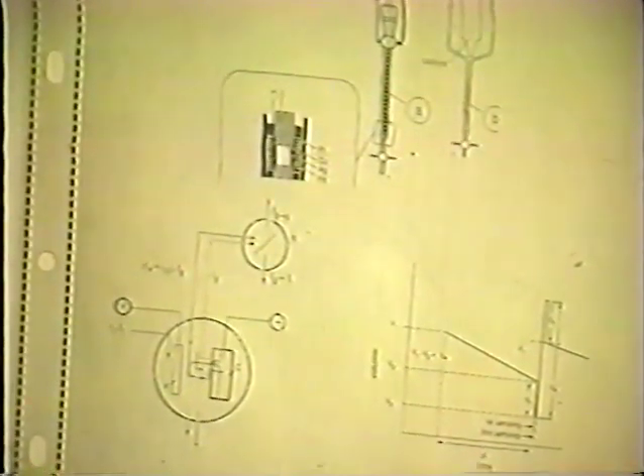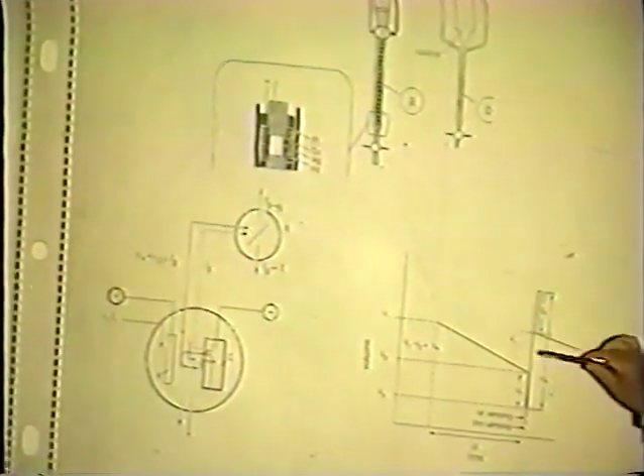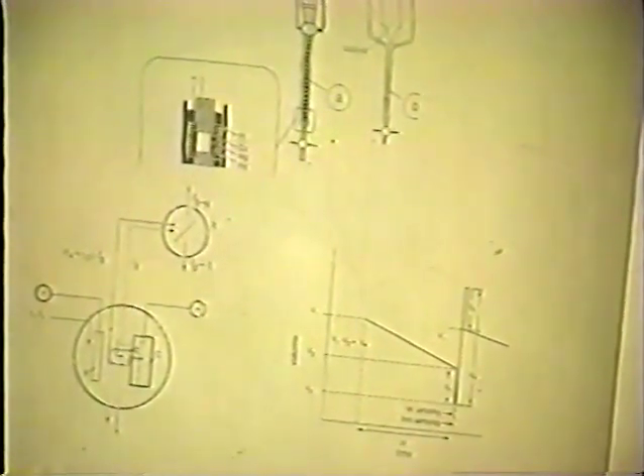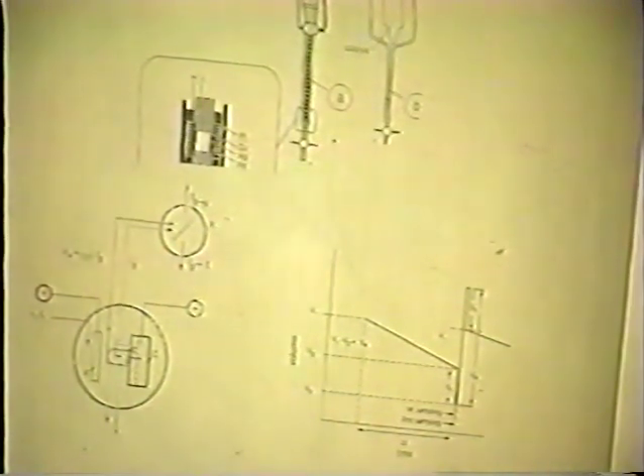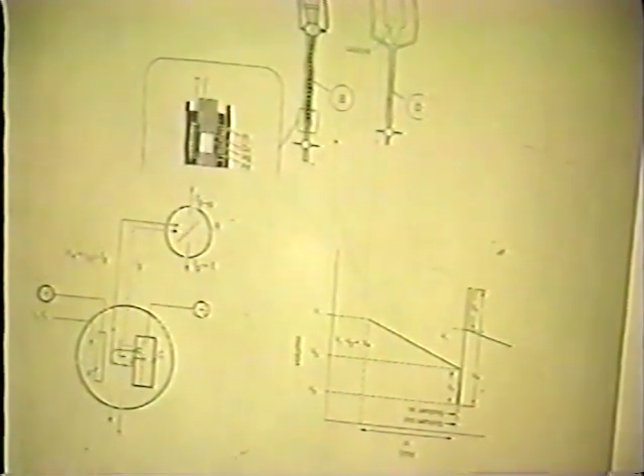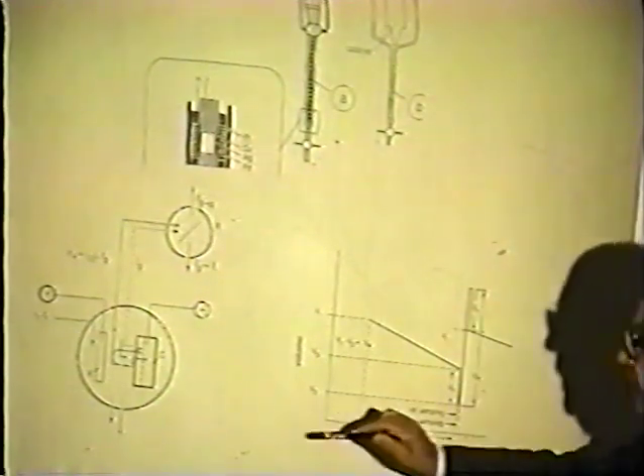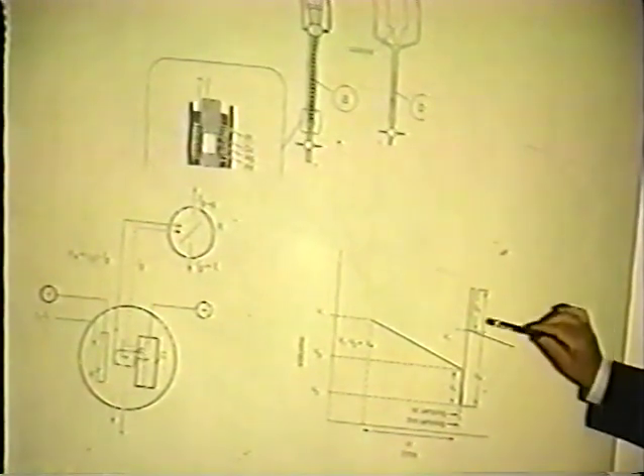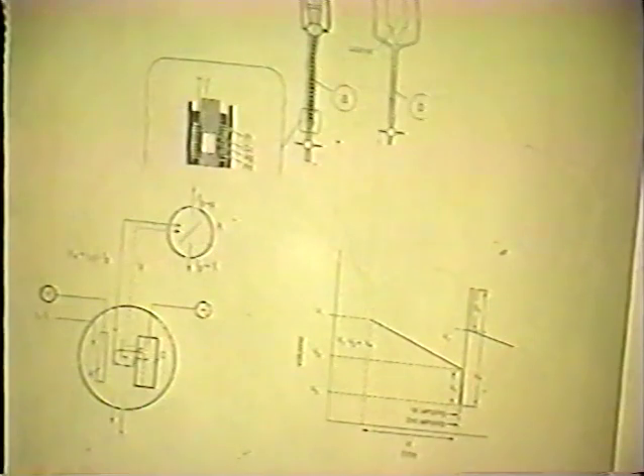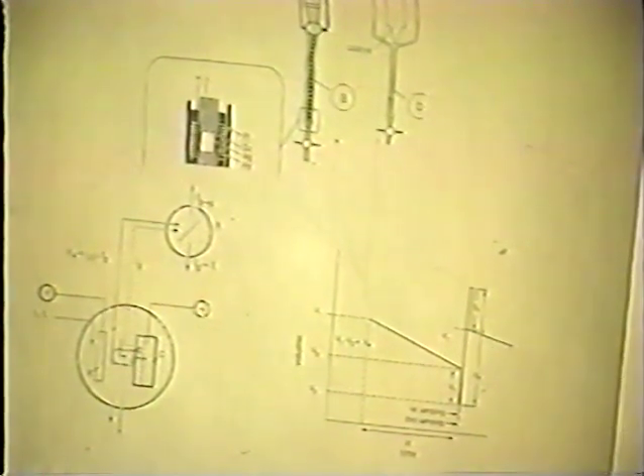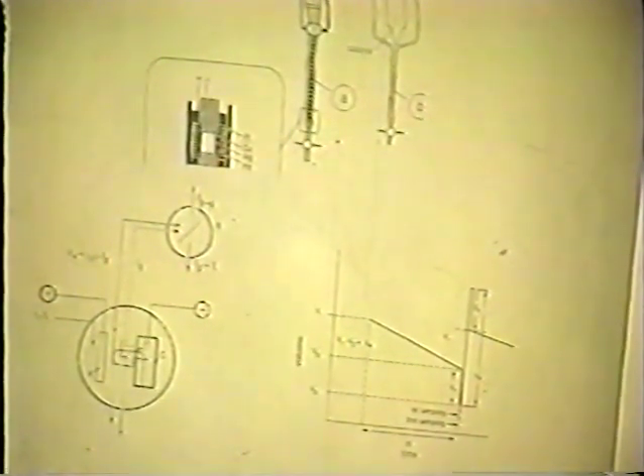What is very important here is the fact that we apply the law of mass conservation in order to determine what should be the composition of the gain or an increase in concentration for a given separation factor. The analysis is done around the electrolyte phase here, and at each time interval we take a sample out for measurements of tritium, we add to make it up, and then a second sample after that to again measure the initial conditions. So this gives us very accurate measurements of the initial conditions that we carry the electrolysis on. Now the results are rather interesting.